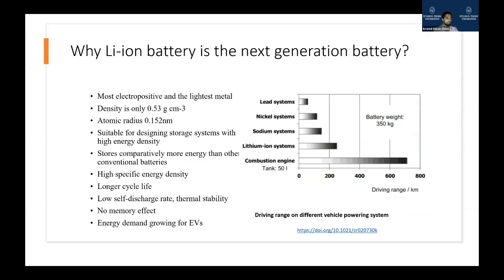So now we will talk about the lithium ion battery, because our next generation battery is the lithium ion battery. And then again, why we are calling it next generation battery, you can see it here. If you see the lead acid system, and if you have just 350 kilogram of battery, and if you put it in an electric vehicle, you can just go 50 kilometers. Then if you get nickel system with 350 kg, you can go 100. But if you have lithium ion system, you can go more than 200, almost 300 kilometer of driving range you can get.